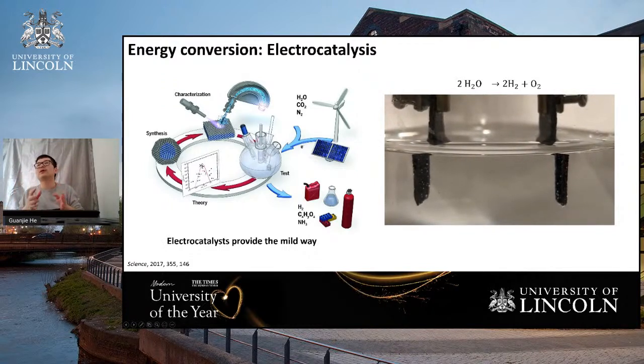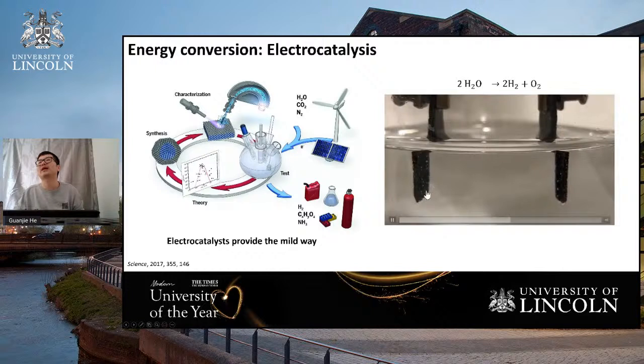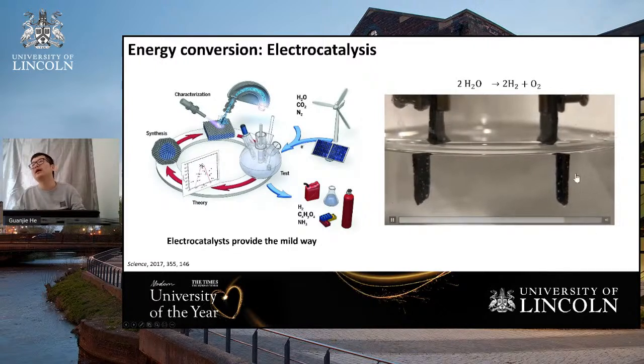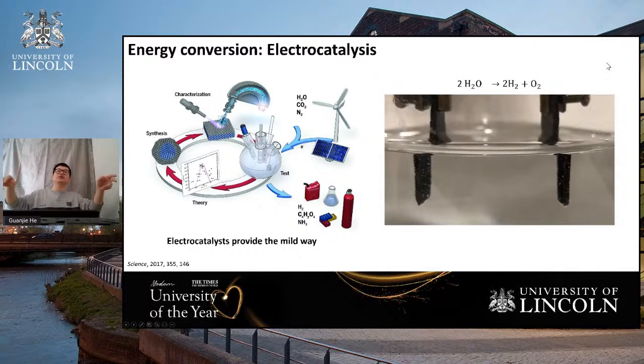For the 2 water molecules, they can generate 2 hydrogen. And you can see there are more bubbles here compared to these electrodes. So this part is the electrode to generate the hydrogen, and this part is the electrode to generate the oxygen. So if we use a chamber or a membrane and put them in different chambers, we can collect the hydrogen and the oxygen for different applications. And we connect those electrodes with another output, that is a potentiostat. It gives extra electricity to facilitate the water splitting.